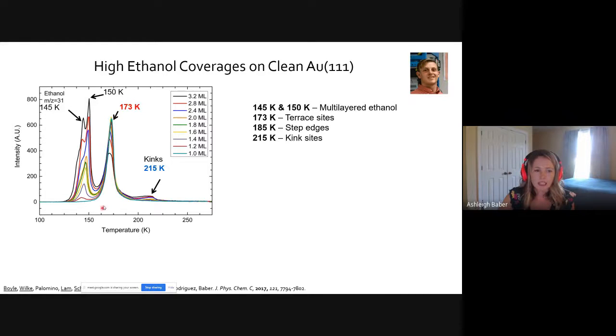Now, interestingly, as we dosed more and more ethanol, we can see that this 173 Kelvin peak, we're able to saturate that. Now it's a little bit harder to see that step edge site, which is again around 185 Kelvin. It's kind of hidden now, but we can see the growth of the first layer of ethanol and the second layer of ethanol. And interestingly, we see this other additional peak pop up at 215 Kelvin.